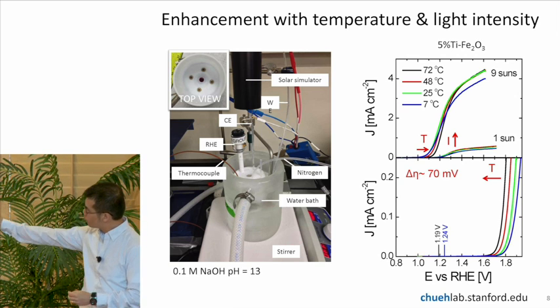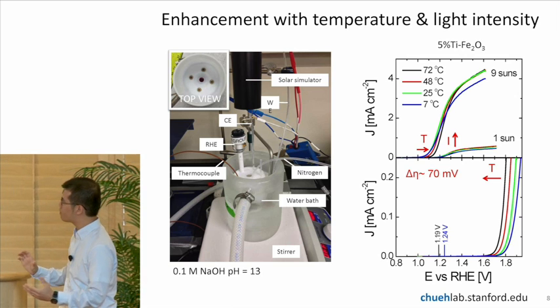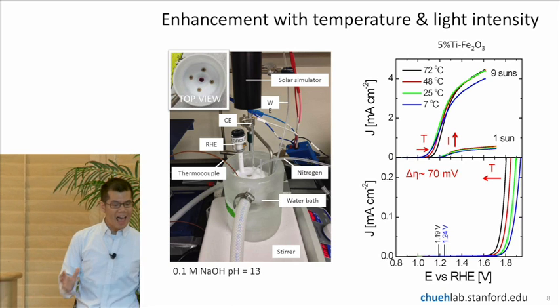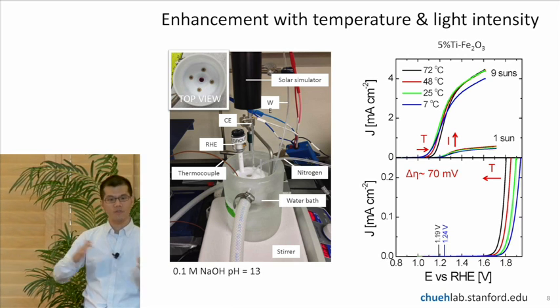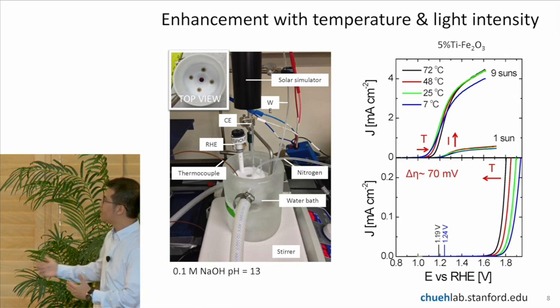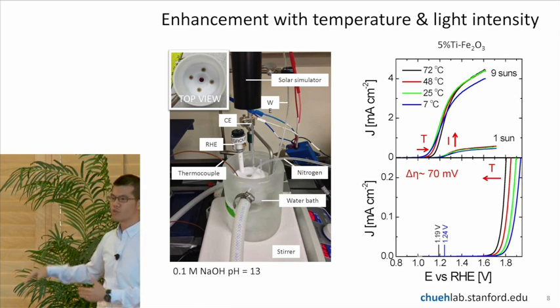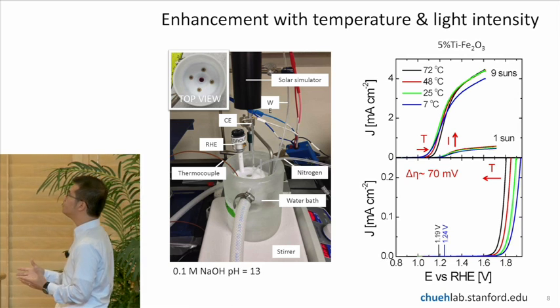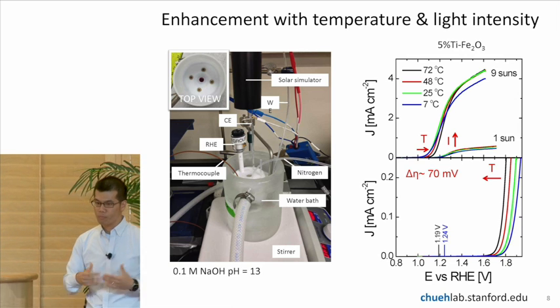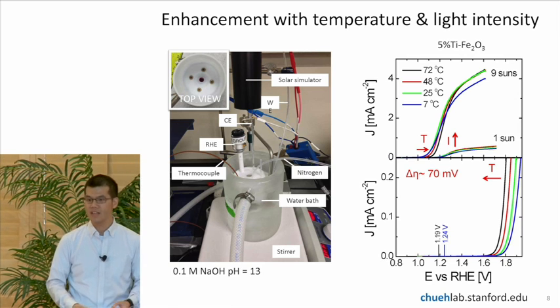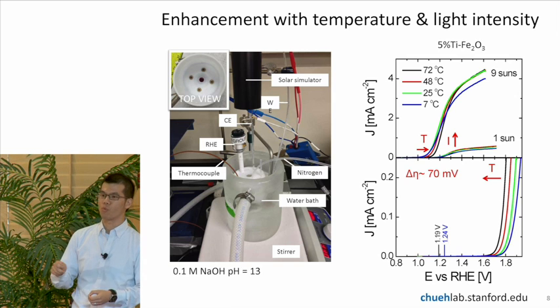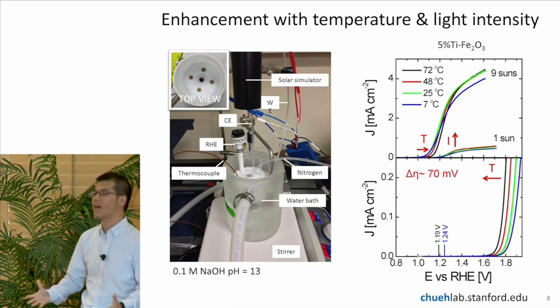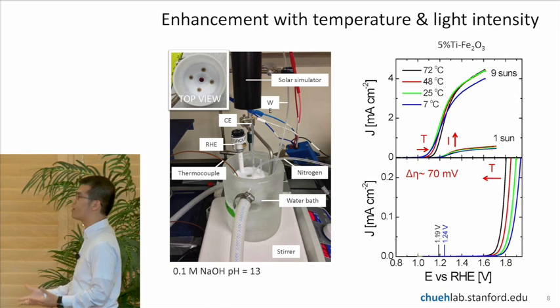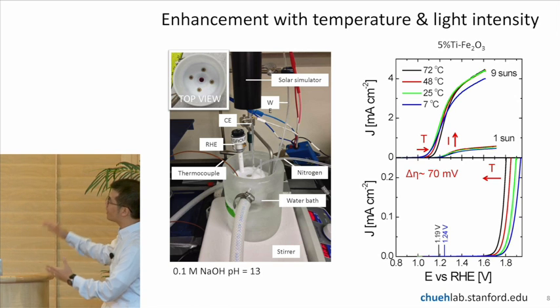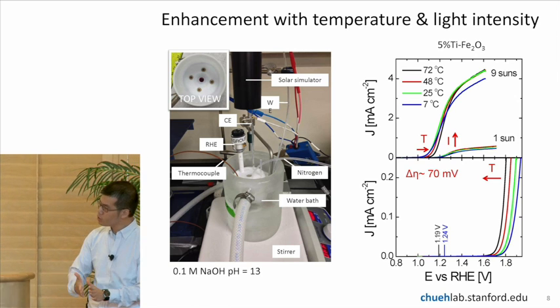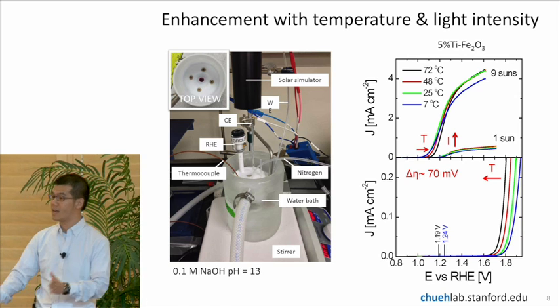And I note that with the 2 voltages on the bottom, it decreases by about 50 millivolts, but the actual voltage decrease we see, the shifting to the left of the plot, is actually much more significant. So from the bottom plot, we can conclude that by increasing the temperature, we're putting thermal energy into the electrons and the molecules to improve the rate of electrocatalysis. So even without light, iron oxide is functioning as a better material. And when we put the light in, it decreases a little bit. The shift is smaller than the gain you're getting, so that's good.